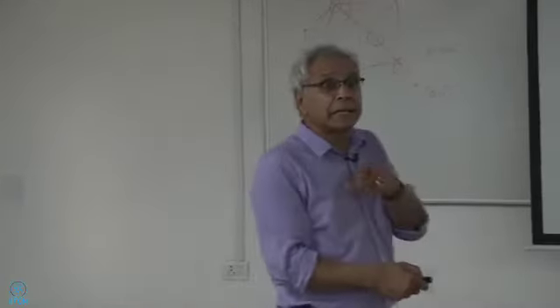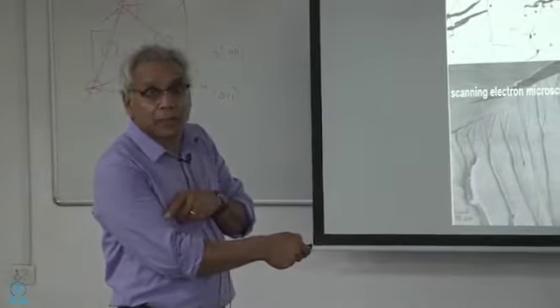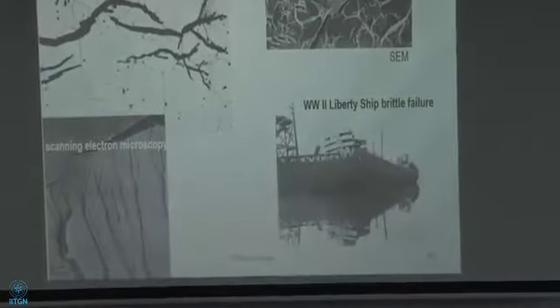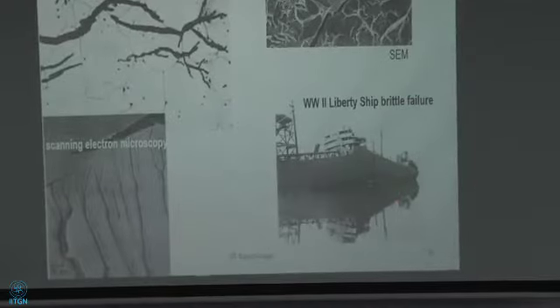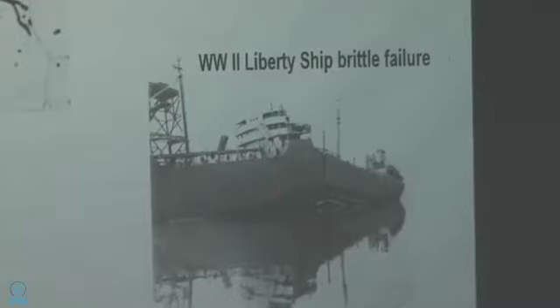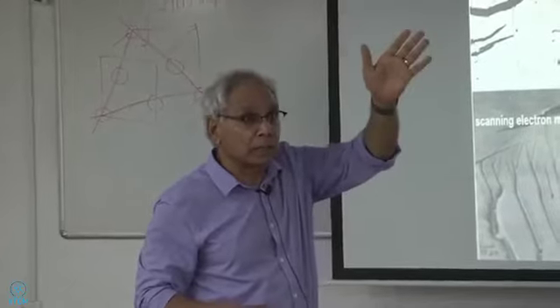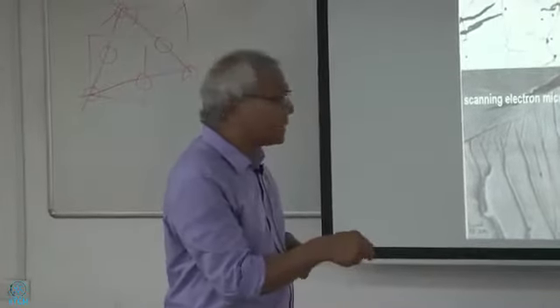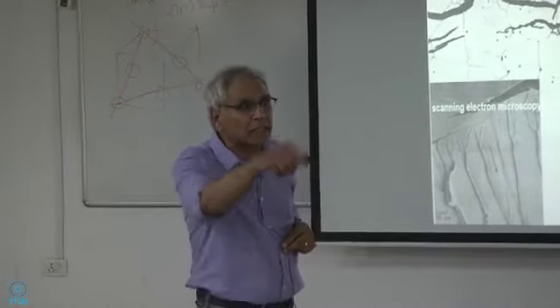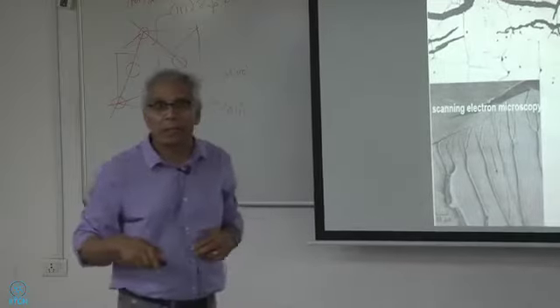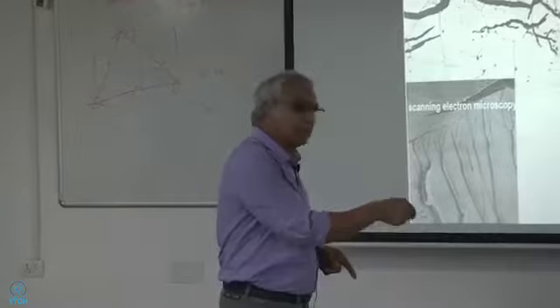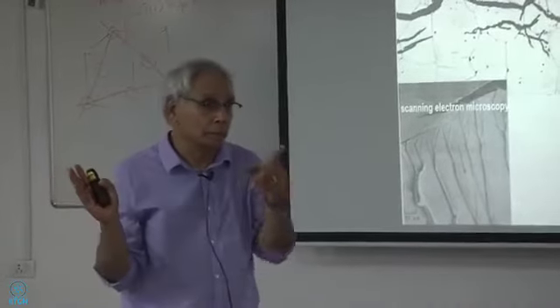The reason I like this is because back in the 40s, World War II, these Liberty ships, how many of you are familiar with this accident? Okay, about 3 or 4 people. These ships broke in half. Literally, this is a crack. It was made of high-strength steel. These ships were stationed in the Arctic Ocean, northern Europe. The day this failed like this, the temperature was just a little bit about 2 degrees Celsius, just above the freezing point of ice. Just 2 degrees Celsius, and it broke into 2 halves because the ductile to brittle transition temperature was way high.